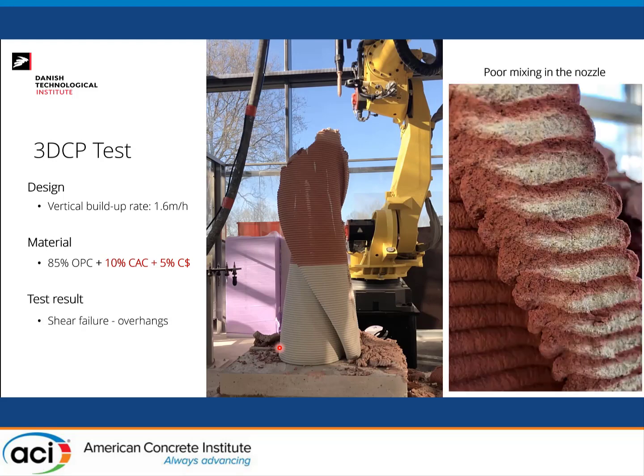But the interesting part is that when we look into what was going on in the layers, it was actually very clear now. It looks like, I don't know, soft ice of vanilla and strawberry, if you like that, if it's warm while you're watching. There was a poor mixing of the two ingredients. What I have to point out is that we deliberately made a slurry. The slurry we were injecting into the system was mixed with red pigment, so we could identify whether there is some mixing of a white base mortar together with a slurry that had the pigment.